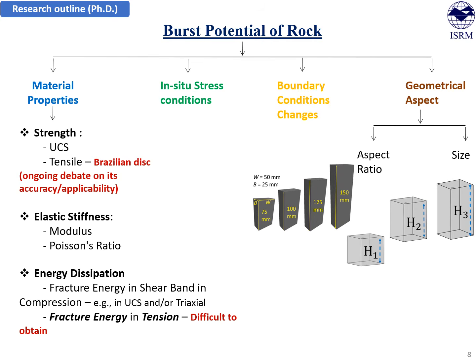And at last, geometrical aspect. There are two categories for that. One is aspect ratio and second is specimen size. When we say aspect ratio, that means if we keep the width and breadth of the specimen constant and keep increasing the height, that means we are changing the aspect ratio of the specimen. And with that change in the aspect ratio of the specimen, how the burst potential of rock is varying needs to be considered.